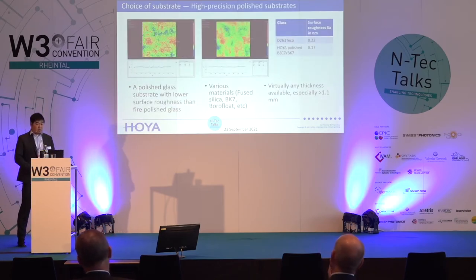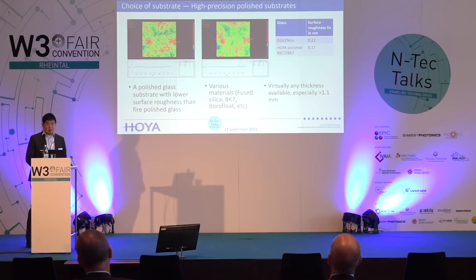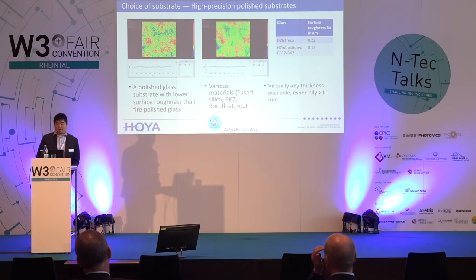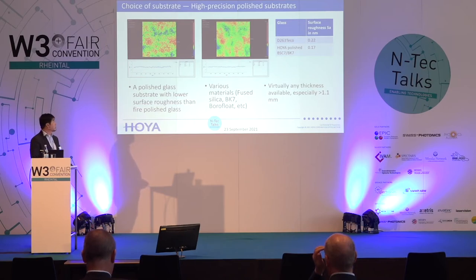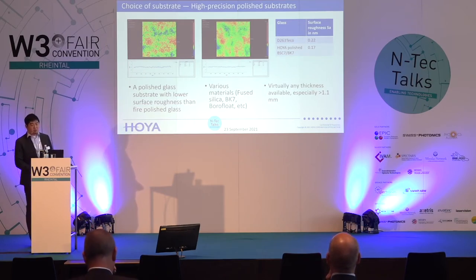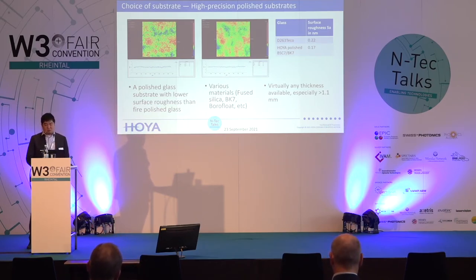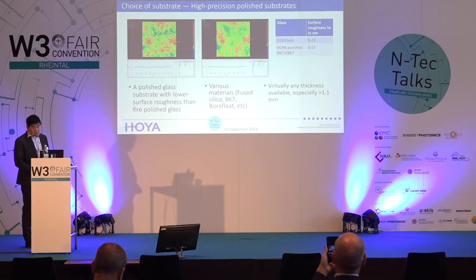One possible solution that Hoya can offer is high-precision polished glass. The advantage is that it can be polished from virtually any of the known materials, and the surface quality in terms of surface roughness can even be better than float glass D263. As you can see in the two plots, on the left-hand side we have the fire-polished glass, and on the right-hand side we have the high-precision polished glass substrate. Here, the advantage, again, is that you can have the surface quality of fire-polished glass with the thickness of any standard material, which can be larger than 1.1 millimeter, to avoid the bending of the substrate.